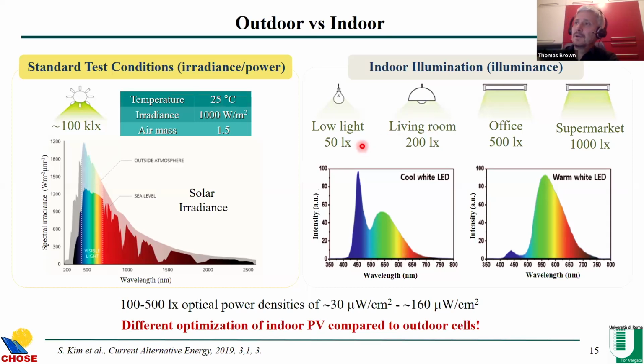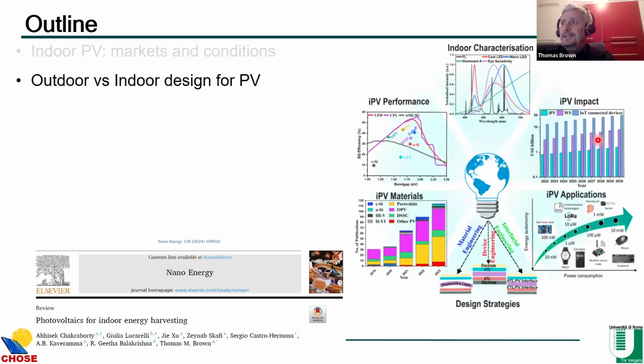So 50 lux can be considered low light, 200 lux living room, 1,000 lux supermarkets. And actually, these are the three main lux levels which are recommended to test your photovoltaic devices. So if you're working on photovoltaics and you want to address their performance, these are the three main levels which are recommended. And the optical power density, going back to the radiometric units, is between 30 and 160 microwatts per square centimeter. These are 2 or 3 orders of magnitude lower compared to the standard test condition, which simulates sunlight. So 100 to 1,000 times less intense than sunlight.